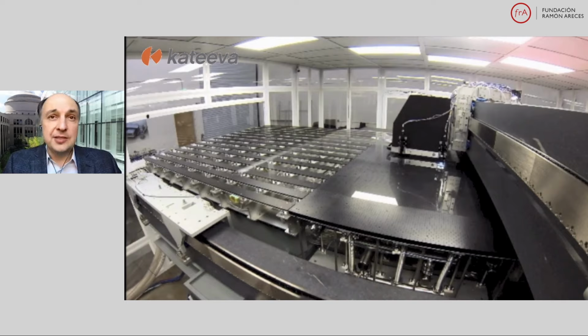The material would be deposited with 5 micron accuracy over a 2 meter substrate. The pixels themselves would be about 25 microns in size. The thickness of the deposited layers would be on the scale of 10 or tens of nanometers. This is a remarkable achievement by our students.